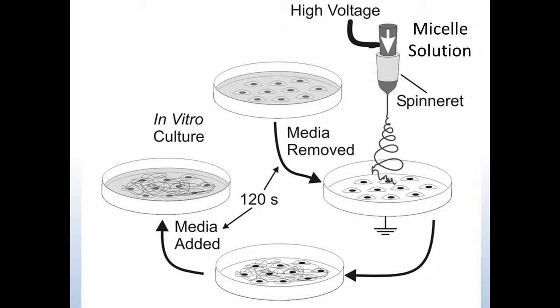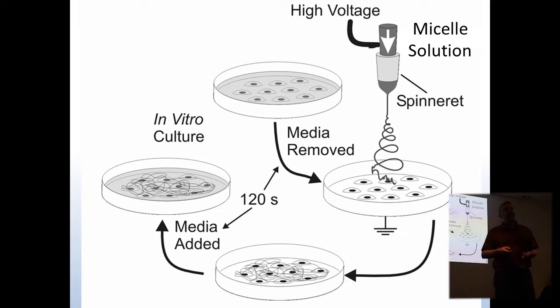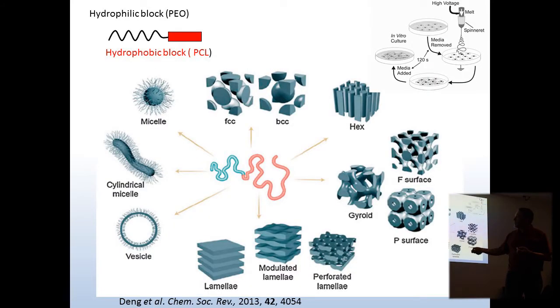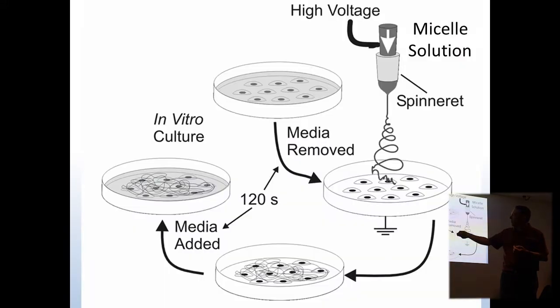What he wanted to do was directly electrospin onto cells. His approach was to have a micelle solution, and so I was given all these block copolymers of polyethylene oxide and polycaprolactone to put into a solution. With a lot of these block copolymers, they have phase transitions. As you change the water content, they can switch from micelles into cylinders, vesicles, and lamella. So the idea was to have at the top micelle solutions and vesicle solutions, so that this will flow very easily. Then as we get solvent evaporation, you get lamella-like structures, and then you can electrospin onto cells.